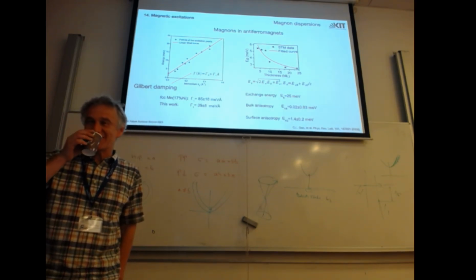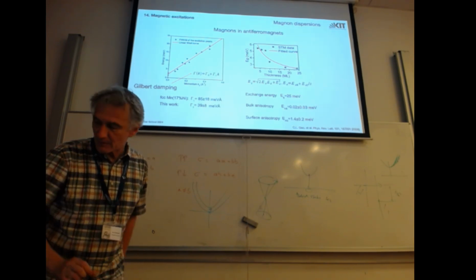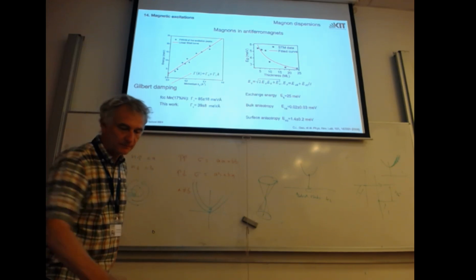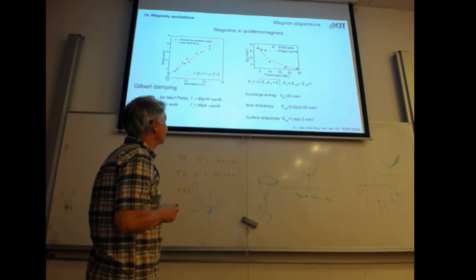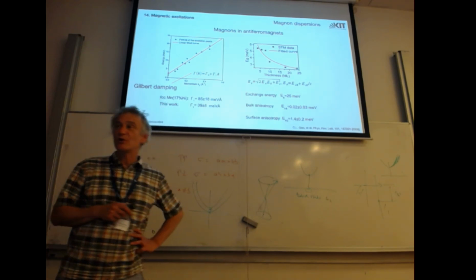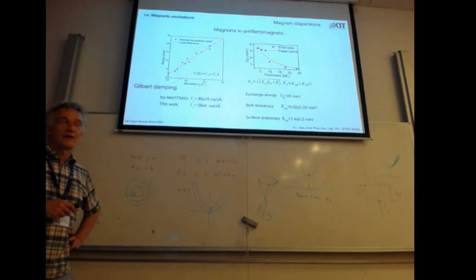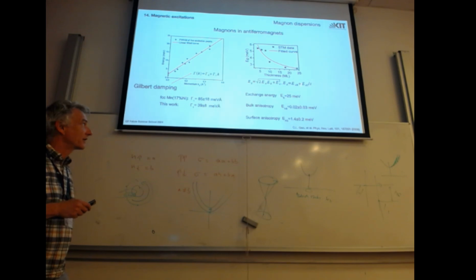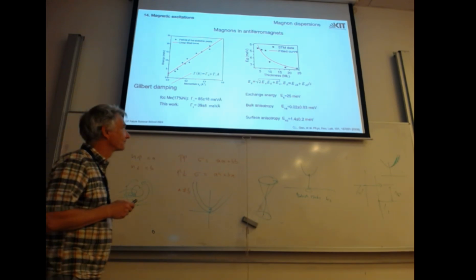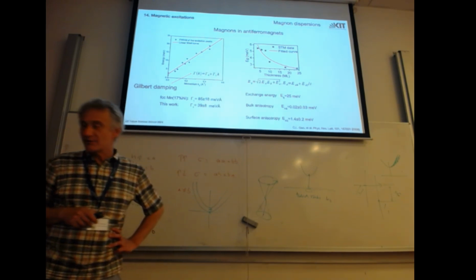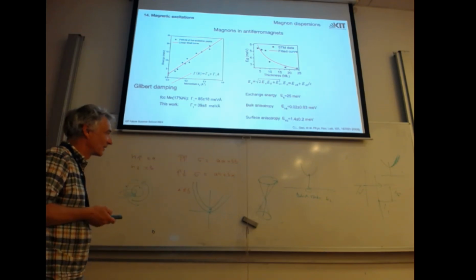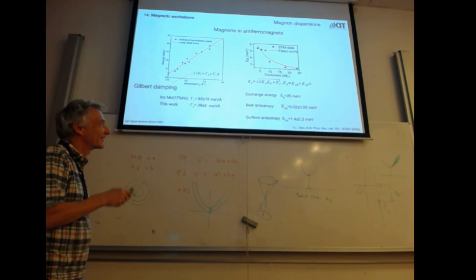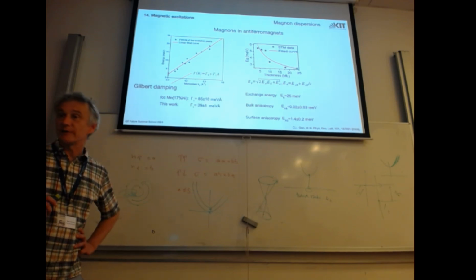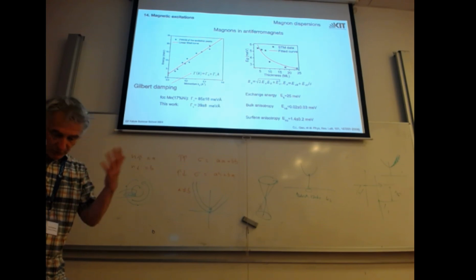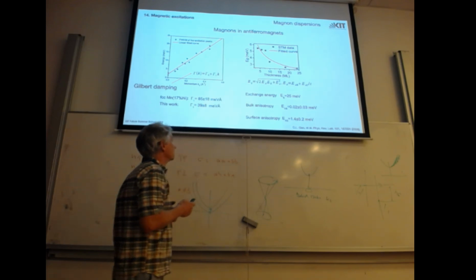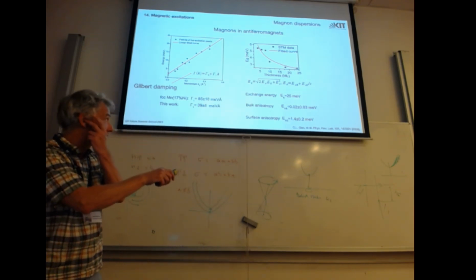So I'm getting maybe a little bit hard to understand. So the surface anisotropy is divided by T, and what is T here? The thickness. So the overall anisotropy density is the surface anisotropy divided by the thickness plus the volume anisotropy. Volume anisotropy and surface anisotropy, but you distribute it over the volume in principle and effectively. You have a change of the anisotropy by the surface contribution. If you plot it as a function of volume, then the surface will go like 1 over T.